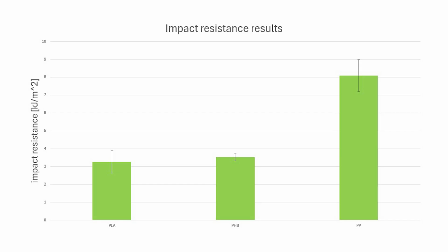By measuring the height reached by the hammer after hitting the sample, we can calculate the absorbed and residual energy. The results of the impact test show us that PP has a higher impact resistance than PLA and PHB. PLA has an impact resistance of 3.3 kilojoules per square meter and PHB has an impact resistance of 3.5 kilojoules per square meter. The value for PP is visibly higher at 8.1 kilojoules per square meter.